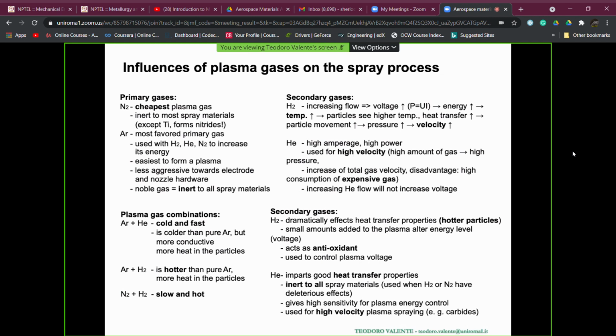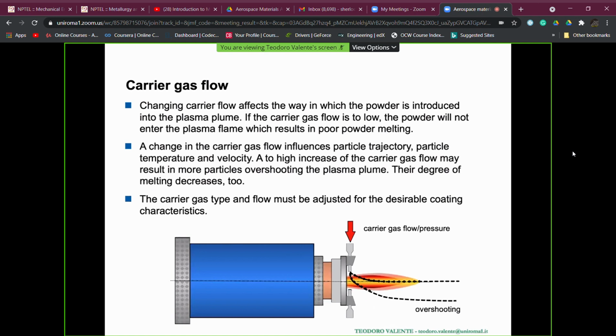Instead, helium has, let me say, a beneficial effect on heat transfer properties, obviously from plasma to the particles. And being an inert gas, as for argon, it is inert to spray materials, so no chemical reaction can be started by using helium as secondary gas. And it's usually used, as has already been said, for high velocity plasma spraying, for example, with carbide-based compositions of powders. The carrier gas flow is important because, as we said, but now we have a picture,